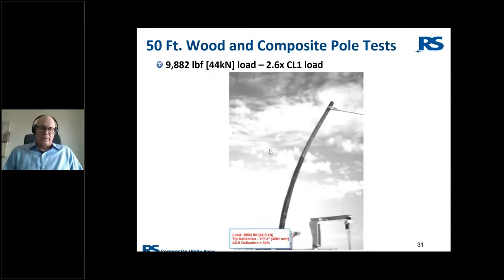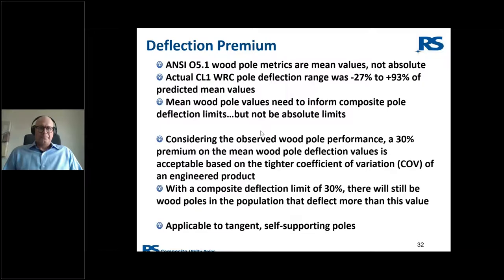And this is the last shot of the composite pole before it failed at just shy of 9,900 pounds of tip load, which is about 2.6 times the class one factored load. And at this high load, the tip deflection of the composite pole was 177 inches, and the above ground height deflection percentage was 34. So where does this take us? This takes us to deflection premium.